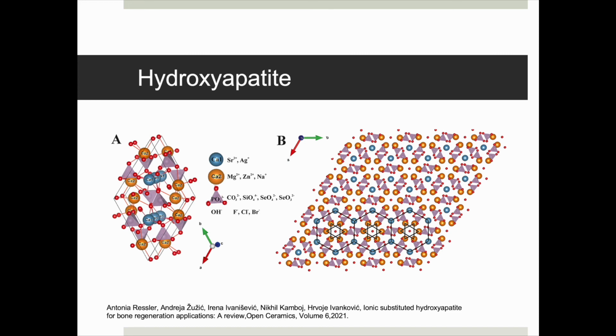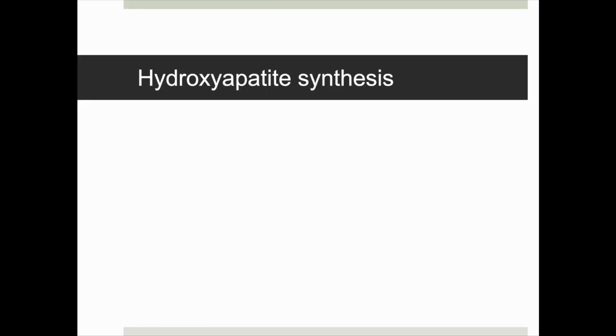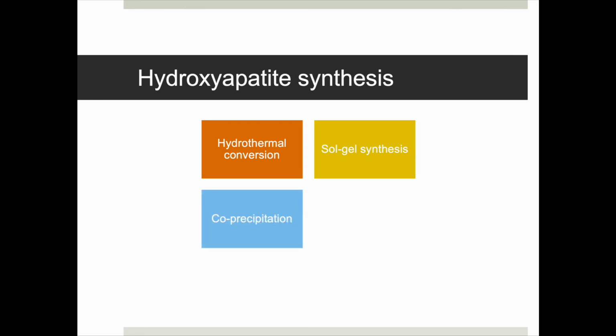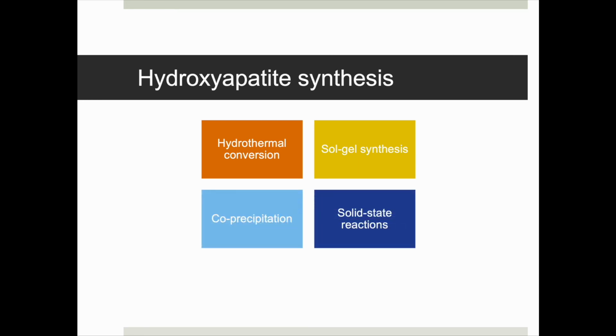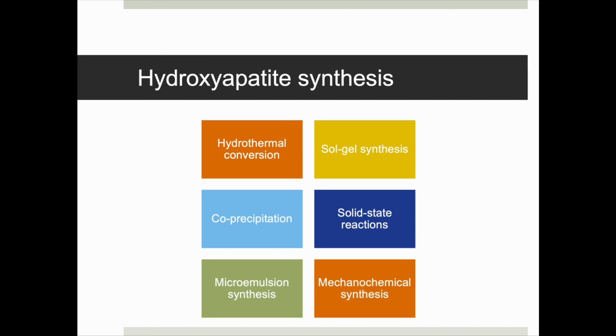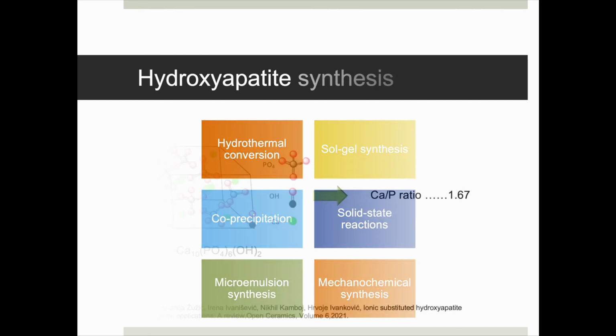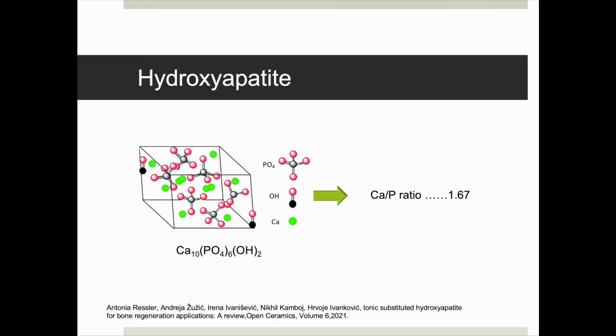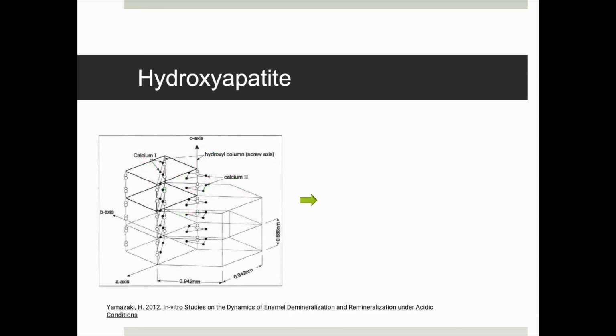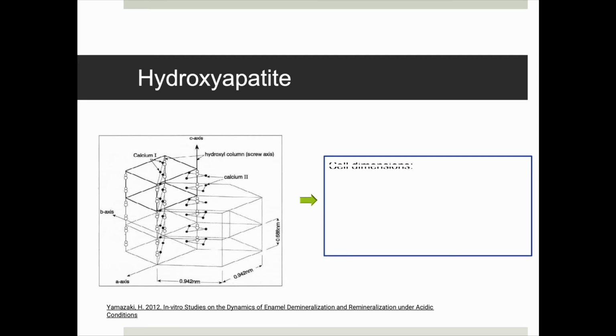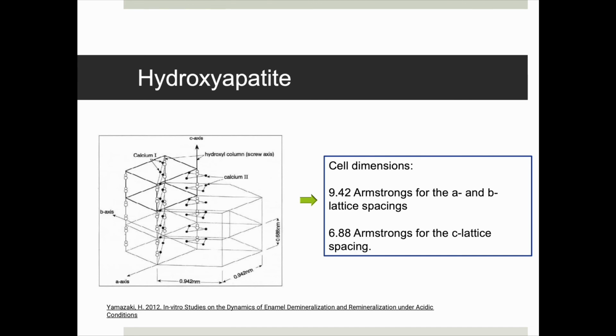Synthetic HA can be produced using a range of techniques, including the following: hydrothermal conversion of natural coral, sol-gel synthesis, coprecipitation, solid-state reactions, microemulsion synthesis, and mechanochemical synthesis. Stoichiometric HA is known to have a calcium to phosphorus mole ratio of 1.67. Structurally, pure hydroxyapatite has a hexagonal close-packed arrangement with cell dimensions of 9.42 angstroms for the A and B lattice spacings and a cell dimension of 6.88 angstroms for the C lattice spacing.